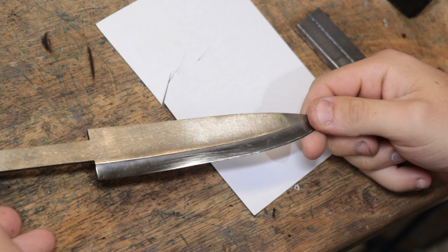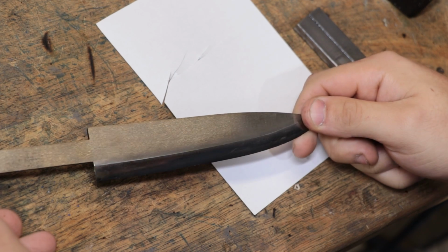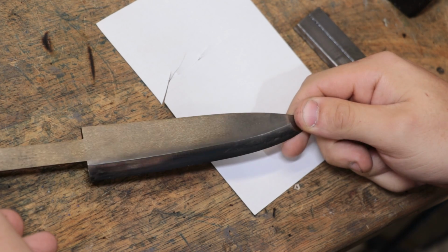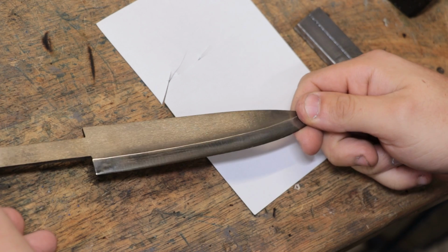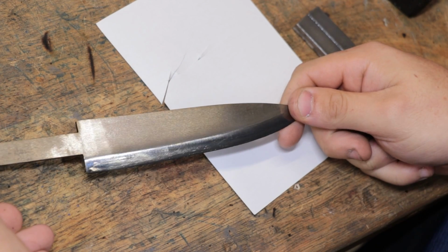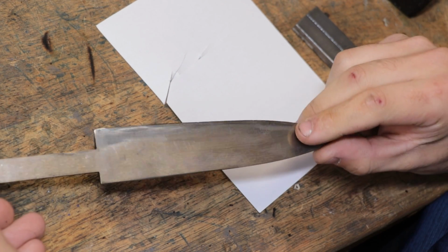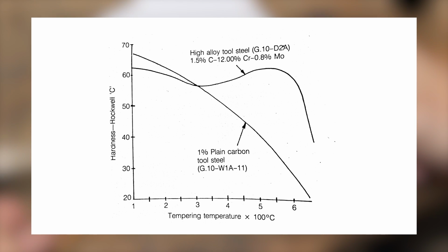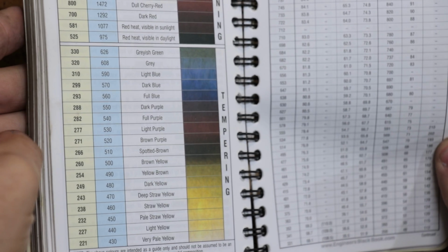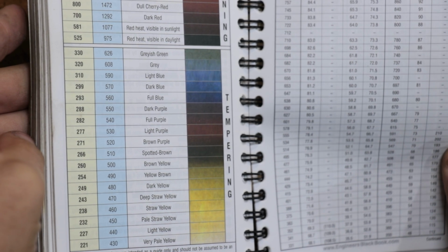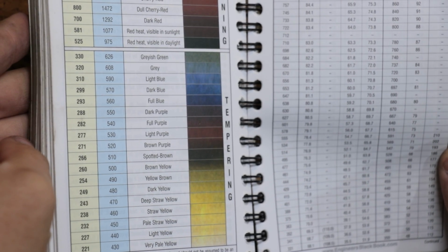Now thankfully, tempering carbon steel is a pretty straightforward process. You heat it to a desired temperature and you soak it there, and the hardness will drop, but the toughness will increase. Now the hardness that you get when tempering is pretty much proportional to the temperature that you temper at, although it's not linear, and there are graphs for each type of steel and the final hardness that you will get. Now some people heat the steel with a blowtorch and use the oxide colour as a sort of guide for the steel's temperature.